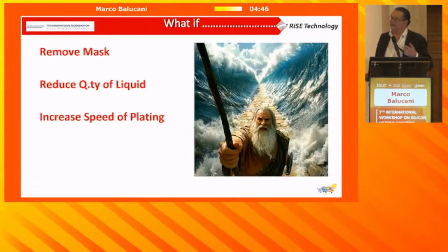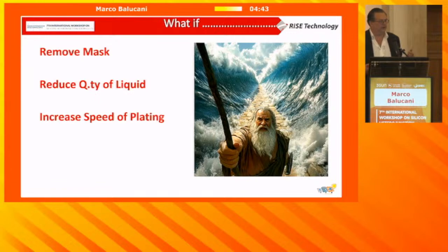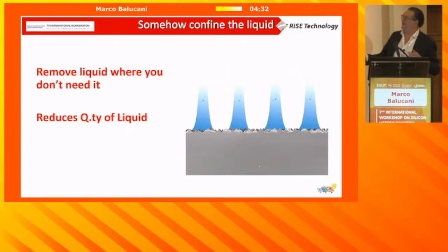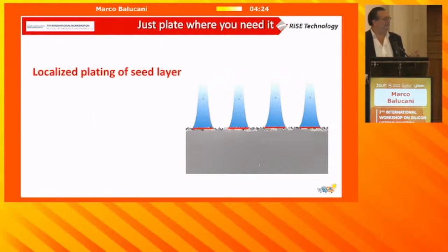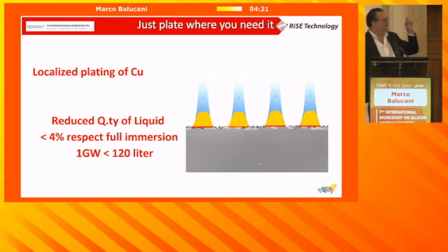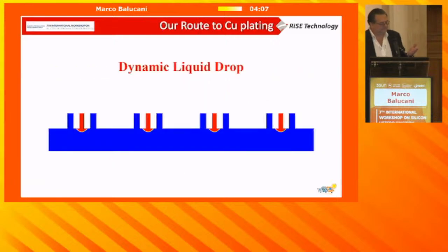So the idea is, can we remove the mask in some way? Can we reduce the quantity of liquids? And can we have some Moses effect that is able to separate the water somewhere and try to do something like this? So, having a confined liquid in some way, we reduce the quantity of liquid that we need. We can make a seed layer, and when we deposit copper, copper will stay inside the liquid, will not go away because the liquid is there, okay? And this means that you are touching the surface only for 4%, imagine the fingers that you have, and then you need quite less quantity of liquid, okay? So that's how we try to do it.